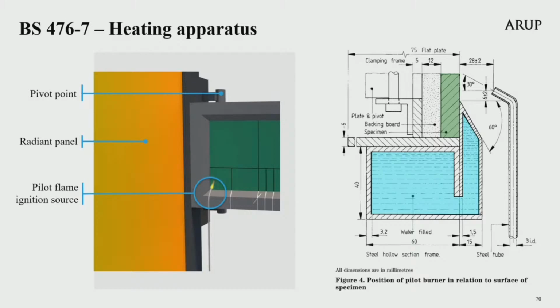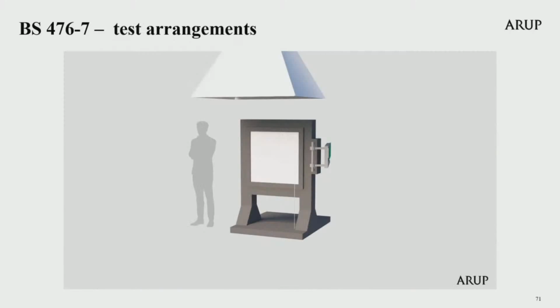The radiation panel shall be fitted with a refractory concrete surround. This surround shall project from the face of the radiation panel on its 4 edges by 50 millimetres. Any small gaps between the surround and the radiation panel shall be tightly packed with a flexible, non-combustible insulating material. A separate small pilot flame is also provided in addition to the radiant heat panel and immediately adjacent to the test specimen. This pilot burner shall consist of a steel tube with an internal diameter of nominal value 3 millimetres and an external diameter of nominal value 6.4 millimetres. The burner shall be designed in such a way that with the specimen in the test position, the centre of the burner is positioned exactly as set out in the standard, which I have reproduced here. The video on screen now shows this test procedure.